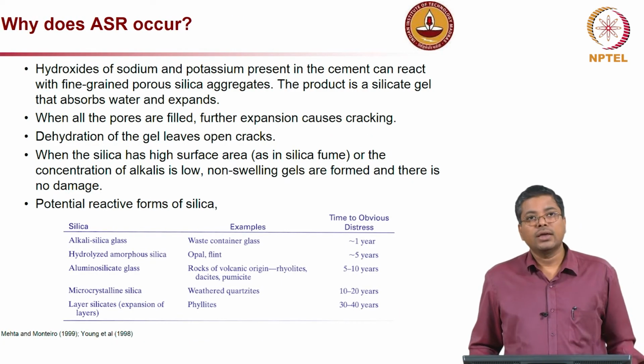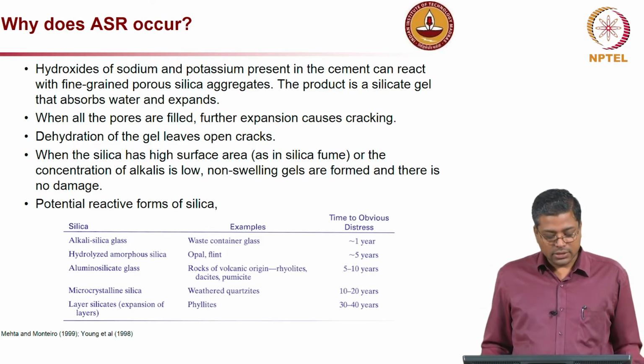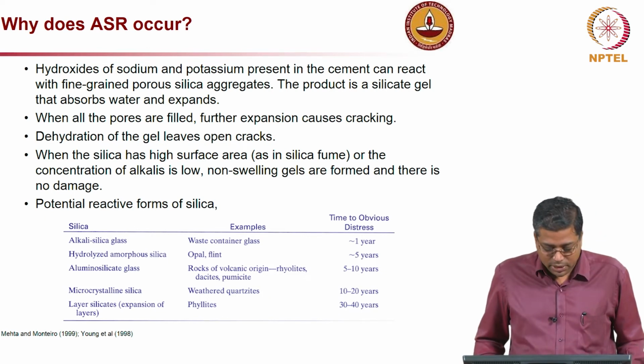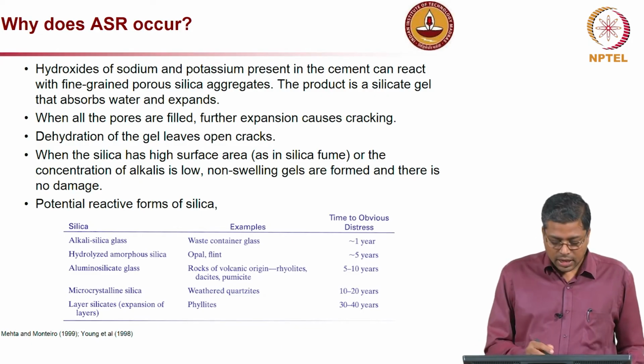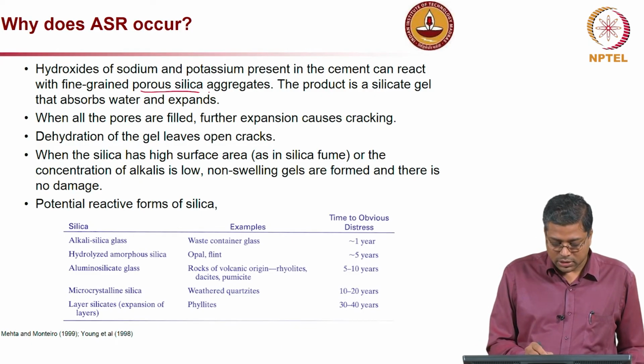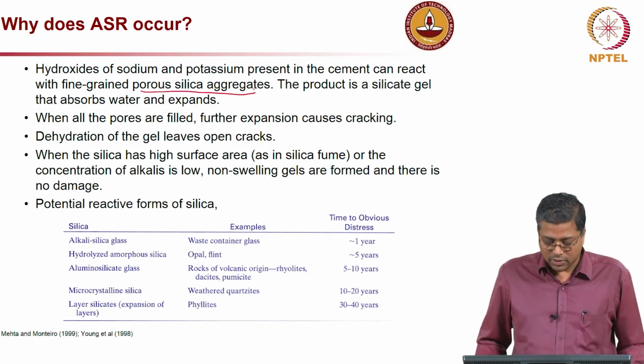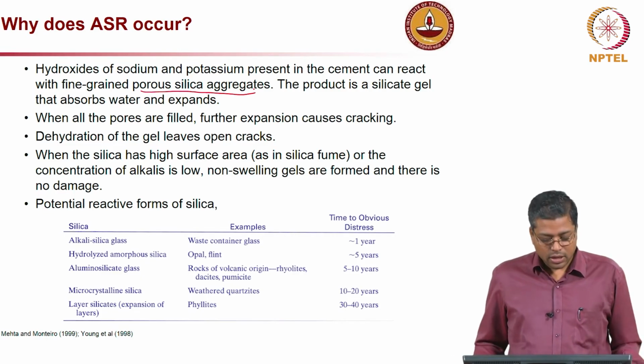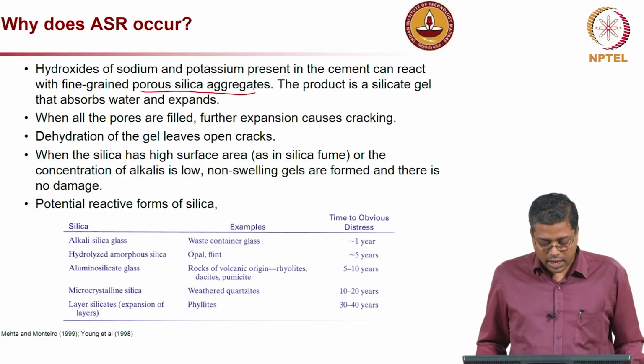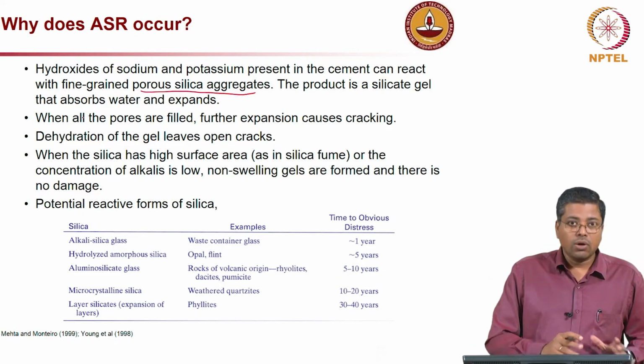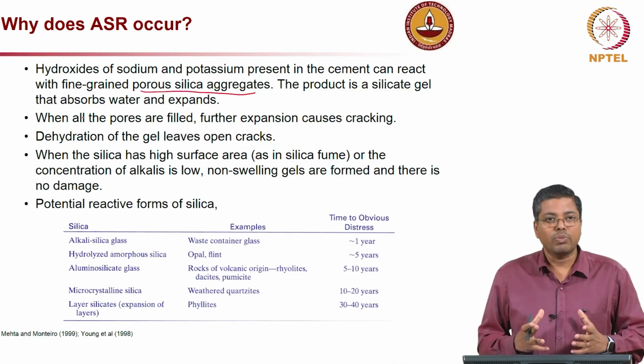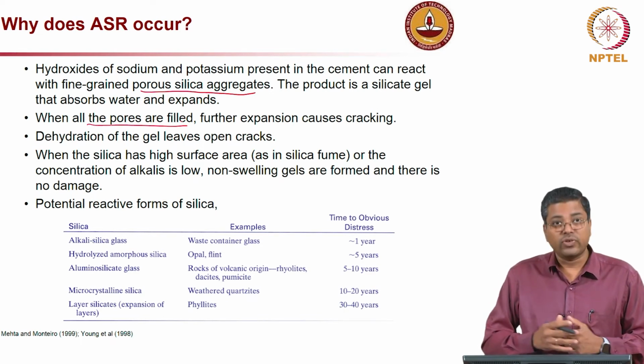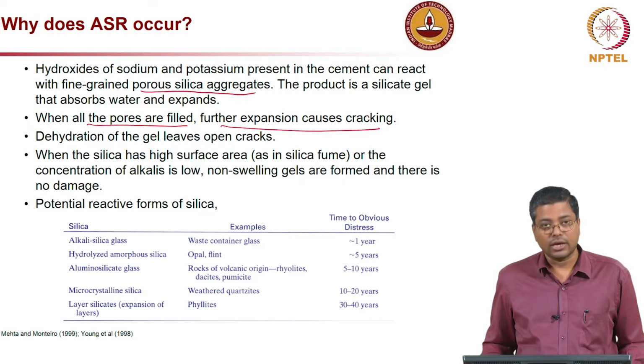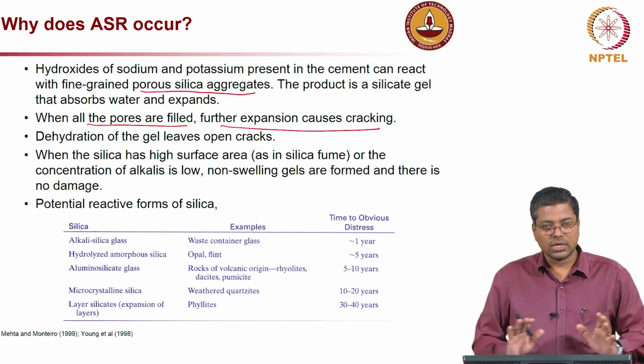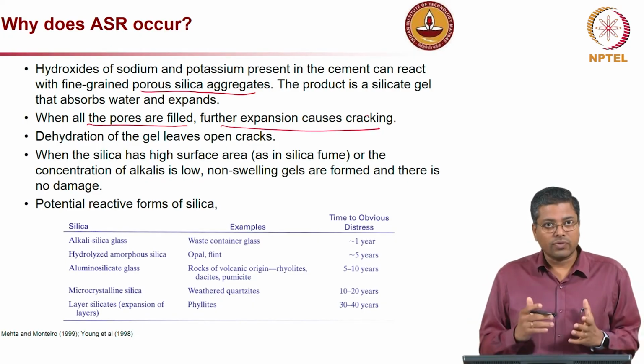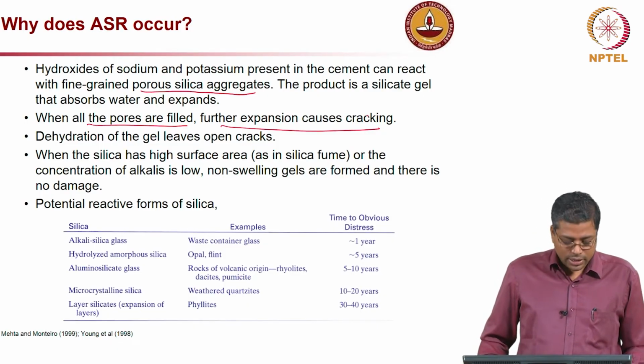Now, let us look at why ASR occurs in concrete structures. As we know, there is a lot of hydroxides of sodium and potassium present in cement, and that can react with the reactive aggregates, which are porous silica aggregates, especially when they are reactive in nature. They will react and form a gel that can absorb water. When it absorbs water, the volume increases and it induces expansive stresses onto the concrete. This gel absorbs the water and occupies all the available pores, and once all the pores are filled, further expansion causes cracking. Until the pores are filled, there is no stress induced onto the surrounding concrete, but once the pores are filled, it starts inducing stress onto the surrounding concrete, leading to cracking.